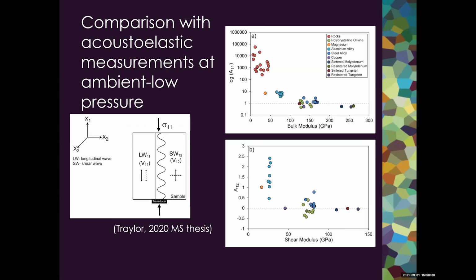So these figures just show the calculated P and S wave acoustoelastic constants of various materials from the literature as a function of the bulk modulus and the shear modulus, in addition to the polycrystalline olivine samples I previously showed. In this upper figure, we have a logarithmic decrease in the acoustoelastic constants with P wave as a function of bulk modulus increase. Here we have these red data points indicating rock data from the literature. And what we can see is that they're scattered at lower bulk moduli. These are experiments that are done at lower confining pressures.